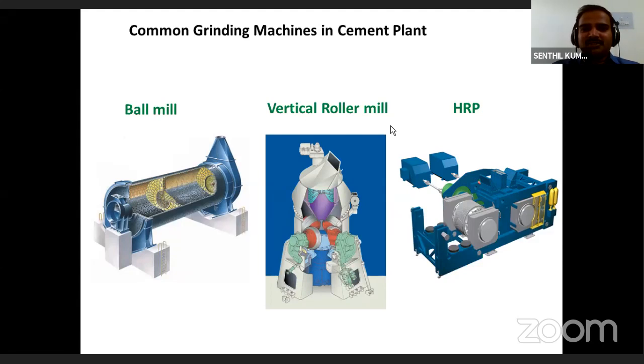For the hydraulic roller press, the width is higher than the vertical roller mills. So what we do is we build up the material, like we hard face, we weld it. For compensating the wear, we weld on the surfaces. We build up the rollers again so that the wear can be compensated, and then the performance can be restored. In all the mills, when the wear rate is higher, then the performance reduces. Any other questions?